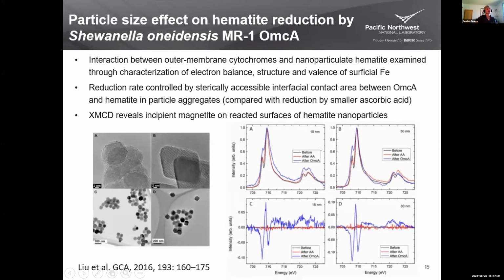And then we used the XMCD to look at that interfacial region and how the cytochrome was interacting with the mineral phase. And what it showed was that if you compare reactivity just with ascorbic acid as a chemical reductant, and with the OmcA, the OmcA localizes the reduced iron at the surface of the hematite, and actually we see from XMCD that there's incipient magnetite formed on the reactive surface because the OmcA cytochrome is able to localize it at the surface and start to catalyze that reaction.